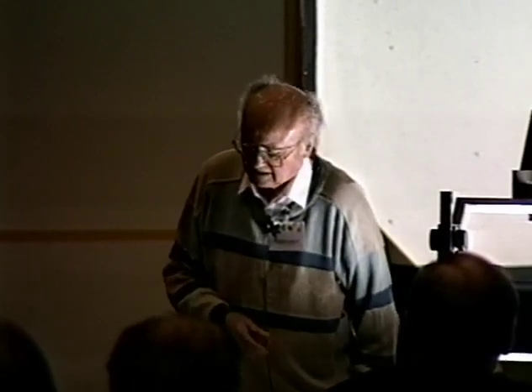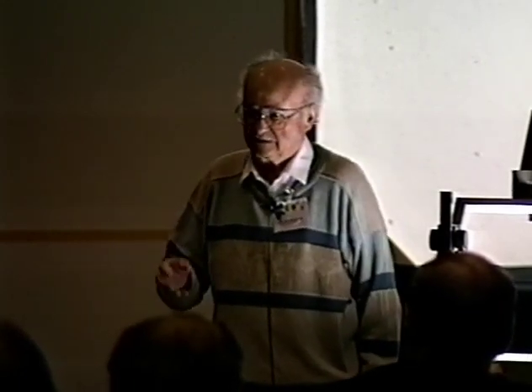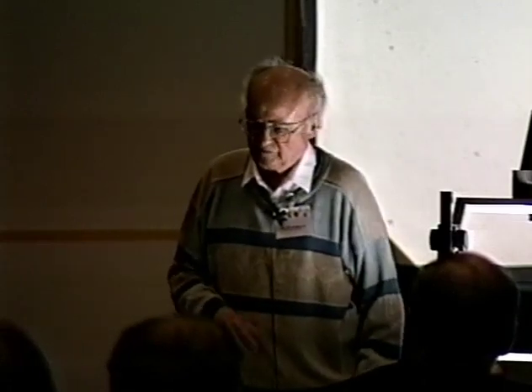After my retirement, I digged in the mud, and I found some of these jewels, and I should like to show you some of them. After some preliminary experiments, where we have painted our preparation to small nickel sheets, and we have heated these in a vacuum and measured the radioactivity before and after heat treatment. But this was not easy. It was a long time taking procedure.